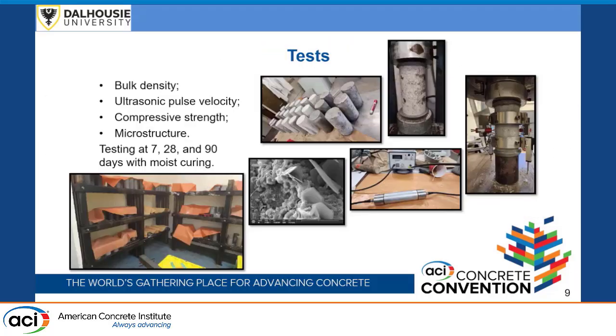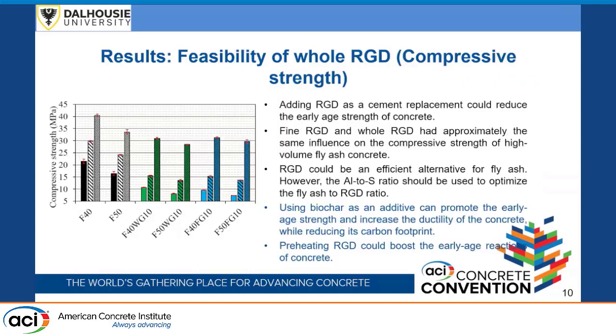So for the tests, as I mentioned in the objectives, we go for bulk density, ultrasonic pulse velocity, compressive strengths, and microstructure. We test the specimens at 7, 28, and 90 days, and we use the moist curing regime. As you can see here, we have a moist curing room and put the specimens in there till the testing day arrives.